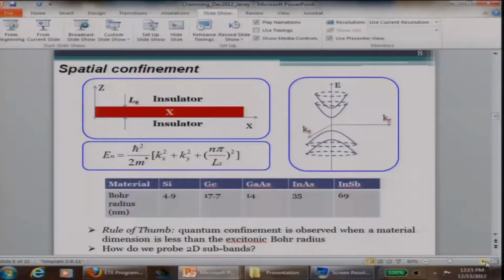Now, from the SEM images and the TEM images that you saw, we have a thin layer of X down to 3 nanometer. You have an insulator, a perfect insulator almost. These are SiO2 or zirconium oxide on top and on the bottom. So effectively, you have a quantum well, close to an infinite quantum well, in fact. If you have a quantum well, then the question is how strong the quantum confinement is going to be. And here I'm showing you a chart of the excitonic Bohr radius of different semiconductors. And the rule of thumb is you get very strong quantum confinement if the thickness is less than the excitonic Bohr radius. So for silicon, as long as you're larger than 5 nanometer, structurally, you will not get too much quantum